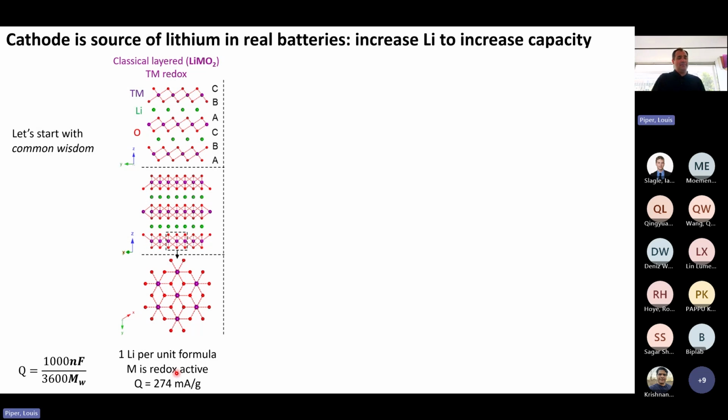And to be honest, when we compare lithium cobalt oxide or changing the ratio of nickel, cobalt, and manganese, we get essentially very similar numbers for the theoretical capacity, because they have very similar atomic masses. But one of the key components is that with lithium cobalt oxide, at first commercial adoption, we were only pulling around 50% of the lithium. We've been increasing the amount of nickel to substitute for cobalt for various reasons, but for the same voltage point, we can increase the amount of accessible lithium to something more like 2/3.